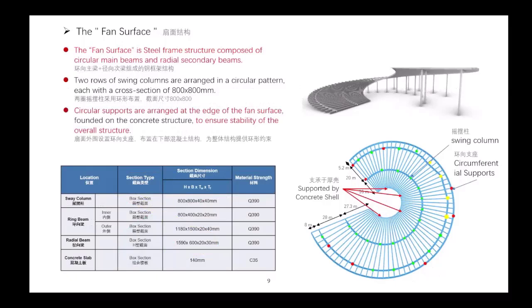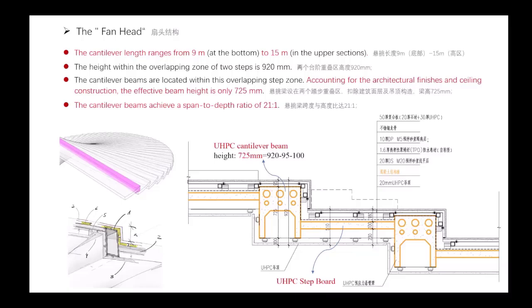The fan surface is a steel frame structure composed of circular main beams and radial secondary beams. Circular supports are arranged at the edge of the fan surface to ensure the stability of the overall structure. The cantilever length ranges from 9 meters to 15 meters, accounting for the architectural finishes and the ceiling construction. The effective height is only 725 millimeters, so the span to depth ratio is 21:1.